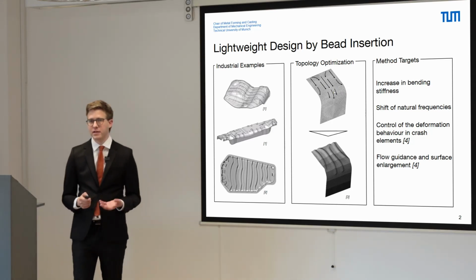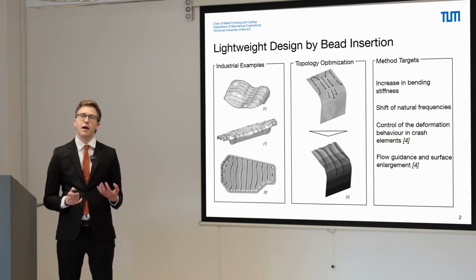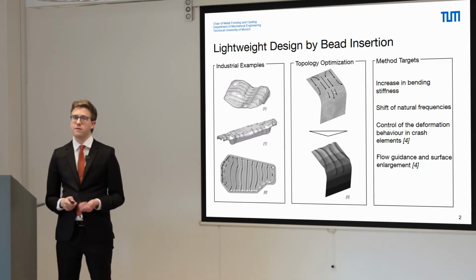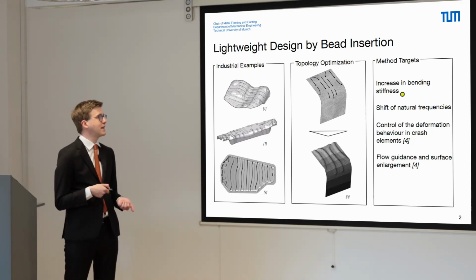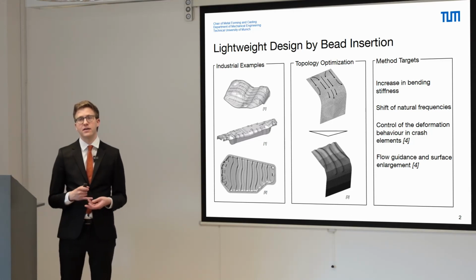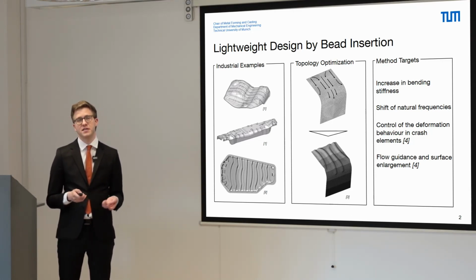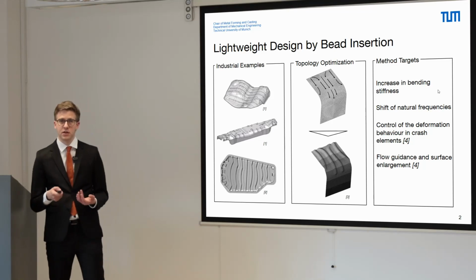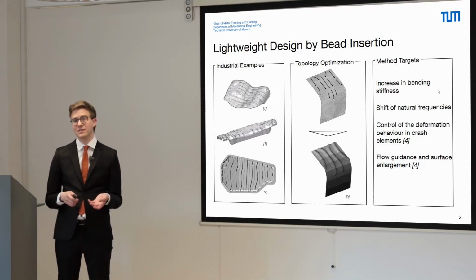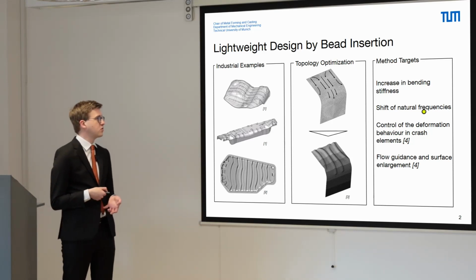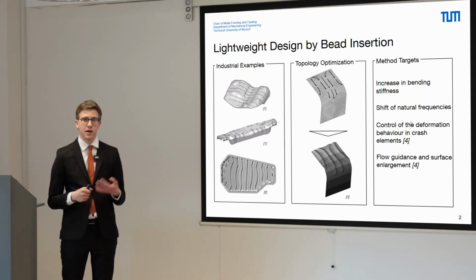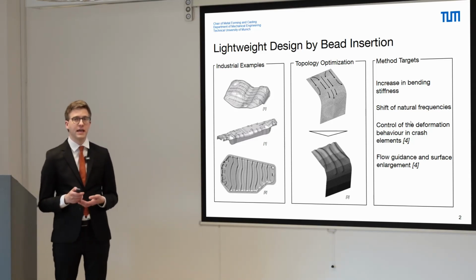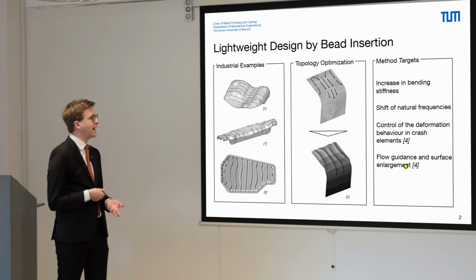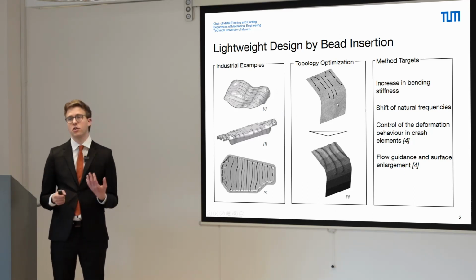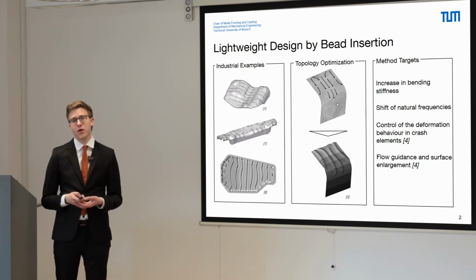To summarize, several targets can be met by integrating beads into sheet metal components. First and foremost, it's an increase in bending stiffness, or when lightweight design goals have to be met, an increase in the mass-specific bending stiffness. Second, a shift of natural frequencies can be used to deal with eigenfrequency and resonance problems. Third, the control of the deformation behavior in crash elements, which is important in the field of automotive industry. And number 4, flow guidance and surface enlargement of the beads show that they can be used for heat transfer problems.